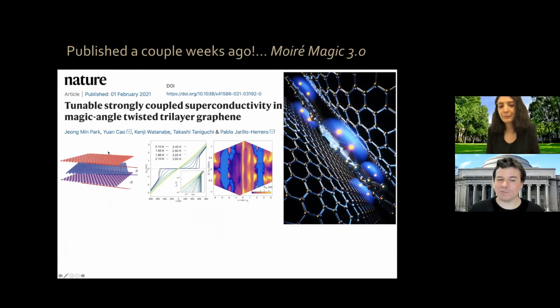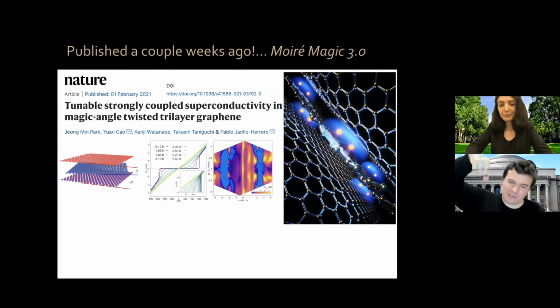And whether a structure is chiral or not, whether it has certain properties, actually affects at a very deep level the properties of the system. In particular, it is believed that in order to have superconductivity, you need to have something called C2 rotational symmetry. It's a 180-degree rotational symmetry around an axis perpendicular to the graphene sheet, okay?